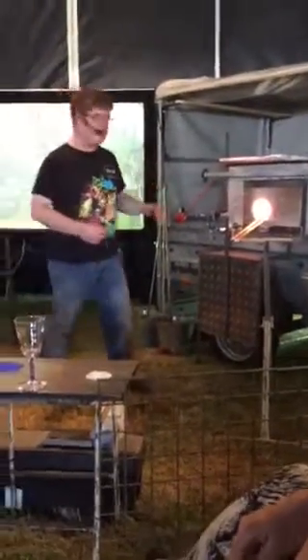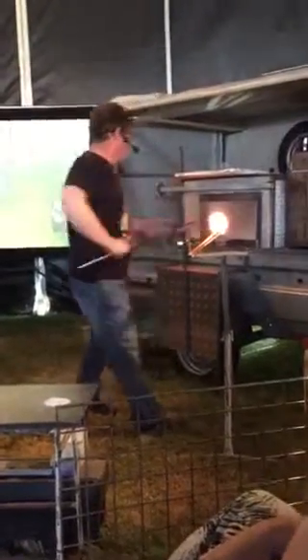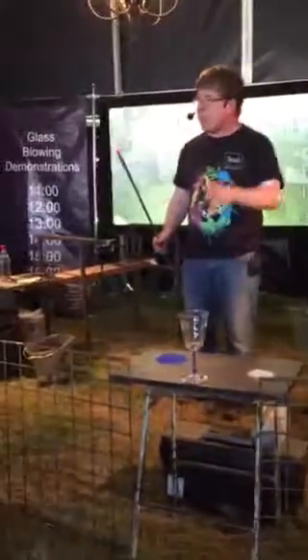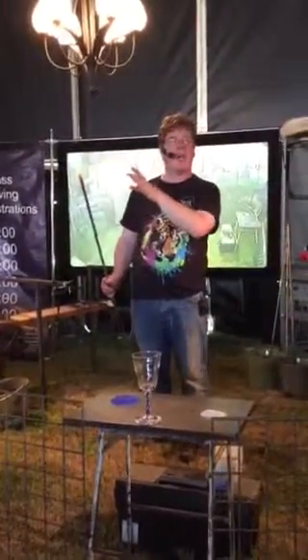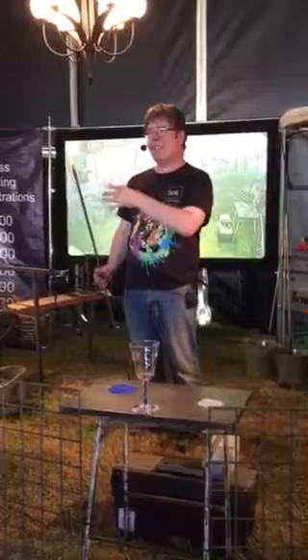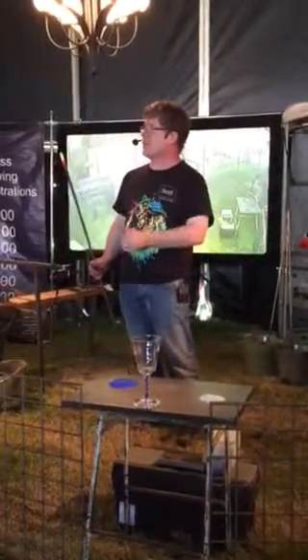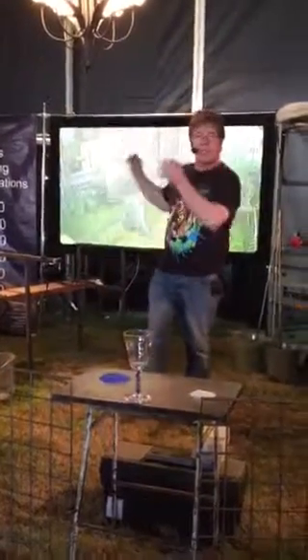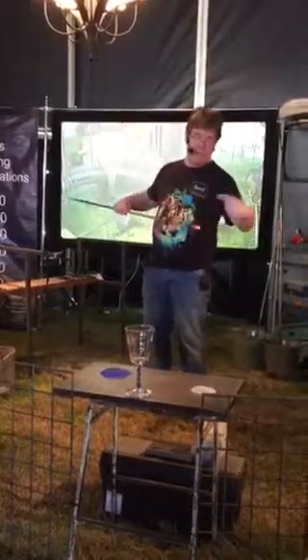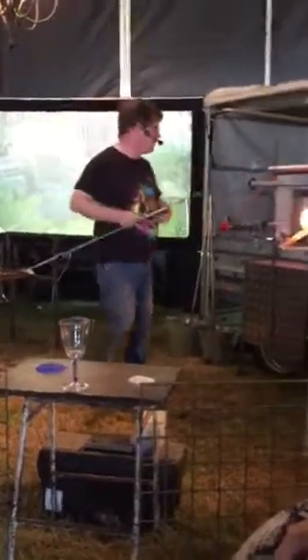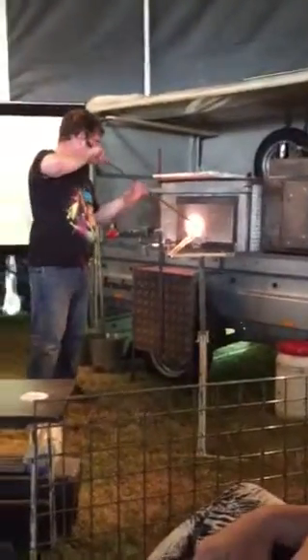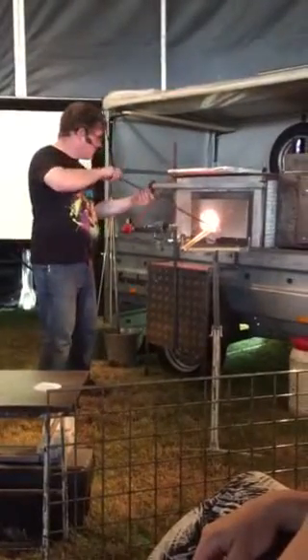Now, if I want to get the glass out of the furnace, the first thing I've got to do is warm up a metal pole. I've got to warm the end up so that it starts to glow like this, because basically if the metal isn't that hot, the molten glass doesn't stick to it. So you warm it to that kind of temperature, you dip into the pool and turn, and basically the glass just wraps around in a spiral. I'll show you that first. Just dip into the pool and turn.